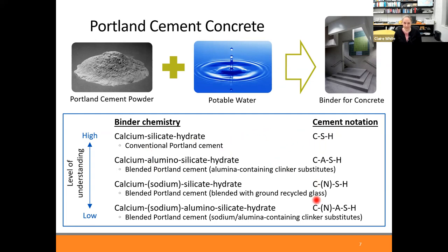What's happening now, as we're trying to reduce the amount of Portland cement powder we need to make a certain amount of concrete, is we're adding in other materials. A good example is calcined clays, and specifically calcined kaolinitic clays. There's a lot of aluminium that comes along. And so what happens is the composition of the gel changes, and so does the structure of the gel. So we have somewhat of a good understanding of this CASH gel, but not as much as the CSH gel.